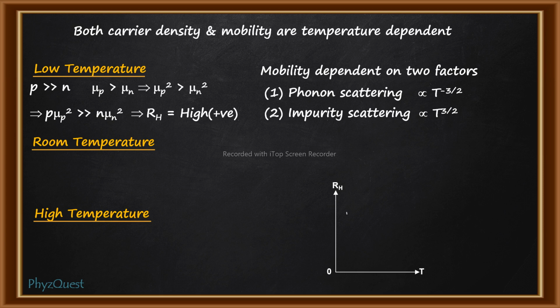Now at room temperature, due to thermal energy, some of the covalent bonds will break and they release free electrons to the conduction band, leaving behind holes in the valence band. Therefore at room temperature there are intrinsic charge carriers, that is both electrons and holes are available, but still the extrinsic charge carriers are dominant here, due to which p is still greater than n. Now at room temperature, as I said, mobility due to lattice contribution dominates. At this stage there is presence of intrinsic charge carriers, that is both holes and free electrons, and in general mobility of electron is higher than holes. So therefore here mu n will be greater than mu p. Therefore mu p square will be less than mu n square.